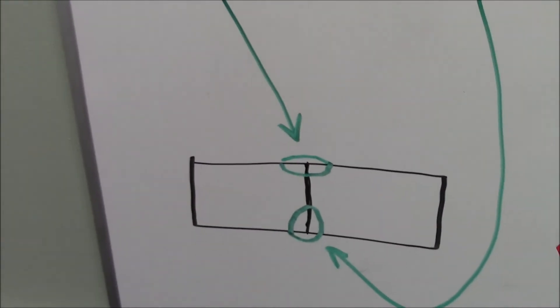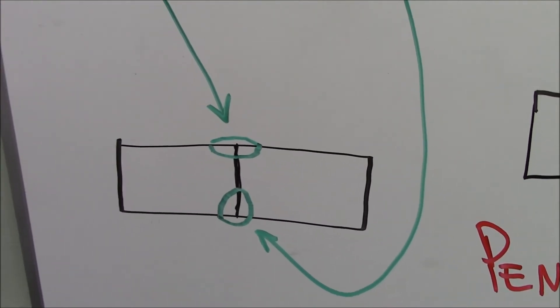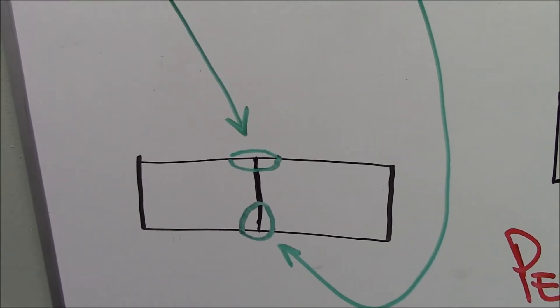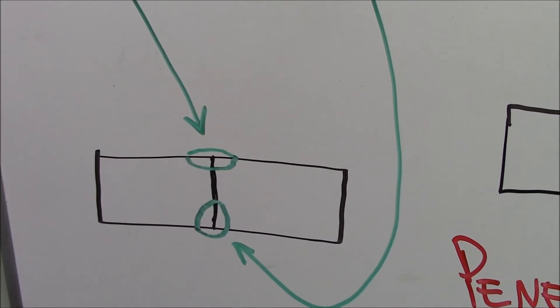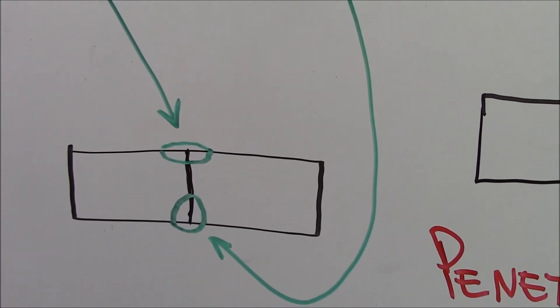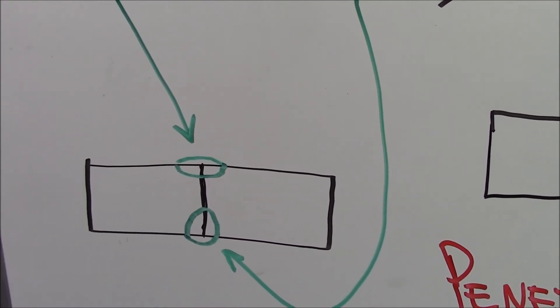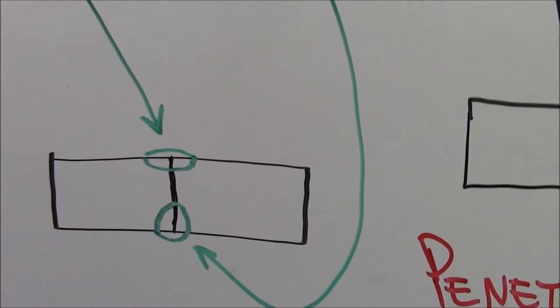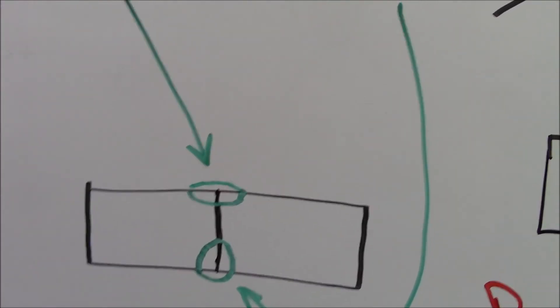So, like I say, if you're doing a square groove joint, then you would want to have either a straight up angle or a slight pull angle to get a deeper penetration. And if you want to put some redundancy in your design that you're going to get a full joint penetration, well, then, whether they're going to push or pull, you can specify in the WPS. But, you would more than likely actually use a beveled groove so that your first pass is going to penetrate down here more and then second, third, fourth, fifth passes. And then, that way, that's just kind of building some redundancy into your joint design.